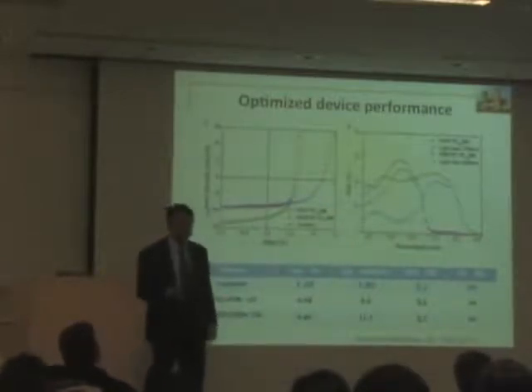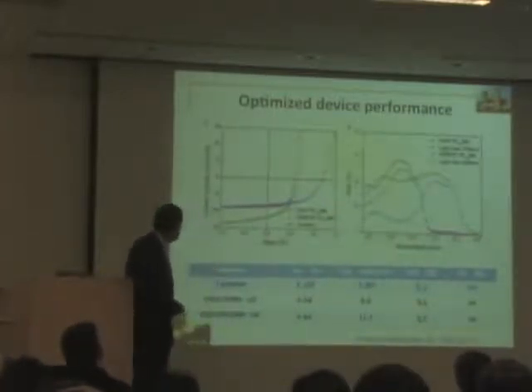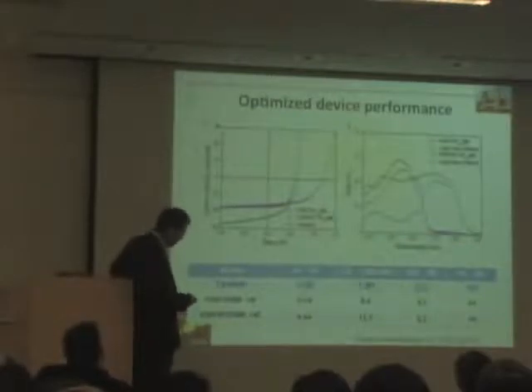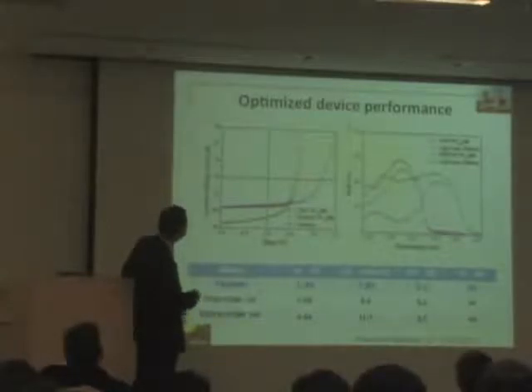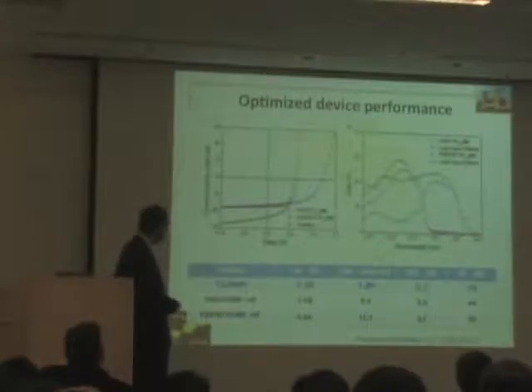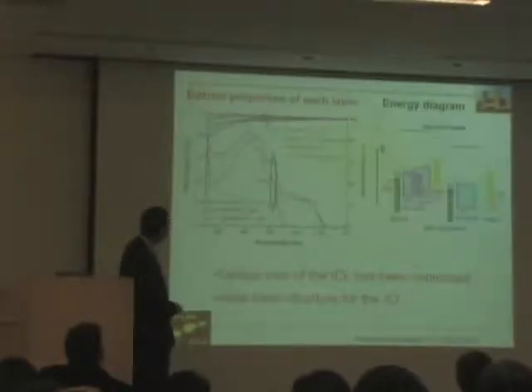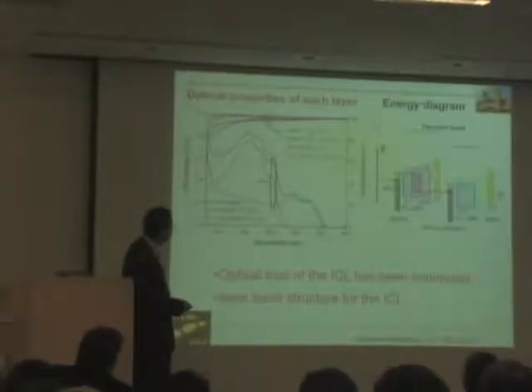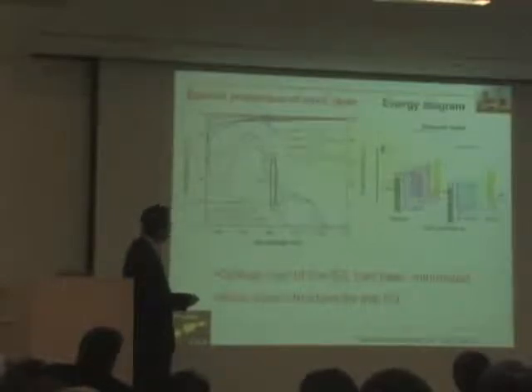So this paper, I believe it's probably 2010, we have the power conversion efficiency of about 5.1% for the optimized tandem solar cell with PSB-TBT. If you look at the band structure, we used moly oxide, aluminum, and zinc oxide at the time, and the aluminum behaves as a Fermi level to pin the PN junction there. This tunnel junction should not be a PN junction. If it is a PN junction, then you're in trouble.